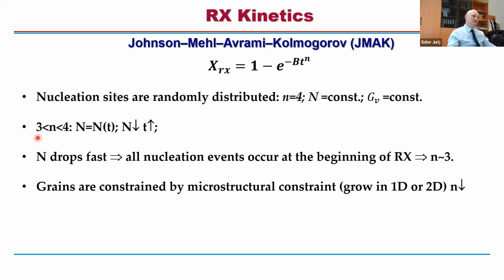what scientists claim is that in fact N is between 3 and 4 when the nucleation rate is time dependent, and in fact the nucleation rate tends to drop during the recrystallization process with time, right? So then in this analysis, N tends to vary between 3 and 4. Normally, when the rate drops fast, all nucleation events occur at the beginning of recrystallization, and these kinetics can be described with N close to 3. That's what we know from various literature sources.